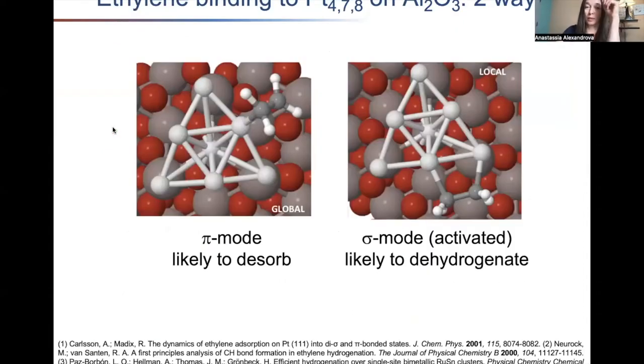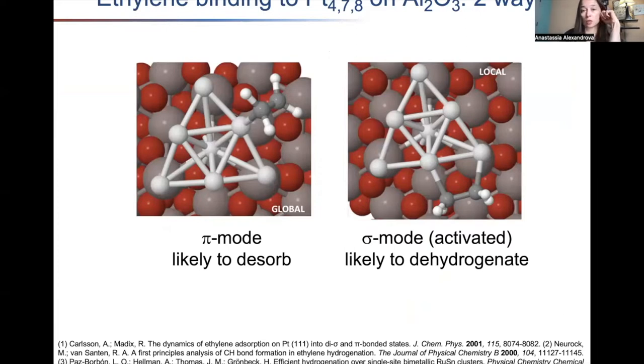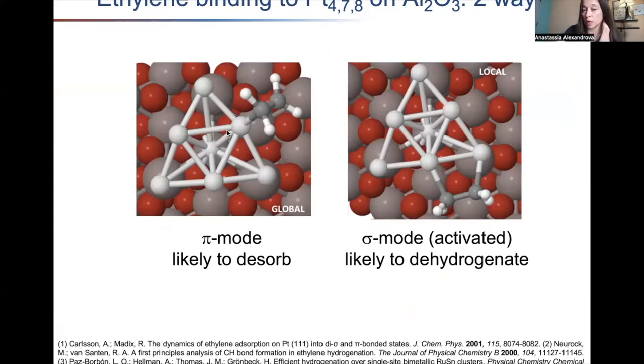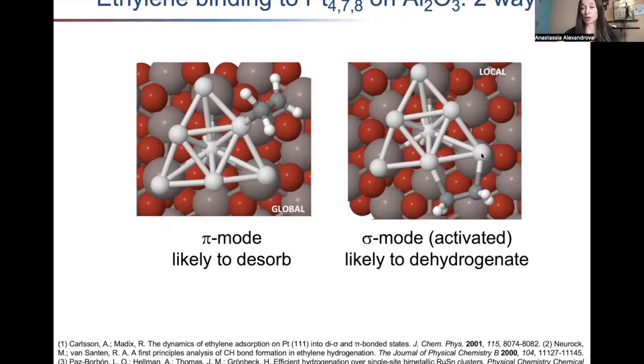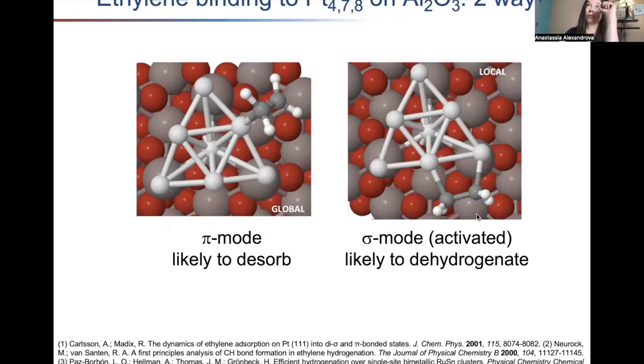For ethylene dehydrogenation, we have a convenient proxy for how likely a given ethylene configuration is to undergo dehydrogenation rather than desorption. Ethylene can bind to platinum in two different ways: first, the pi mode where both carbons bind to one platinum and retain sp2 hybridization; or the di-sigma mode where both go sp3 and bind to two platinums, using two unpaired spins on platinum. We take my soup of clusters, bind up to three ethylenes per cluster — which we know from experiment — and count the percentage bound in di-sigma mode as an indicator of activity.